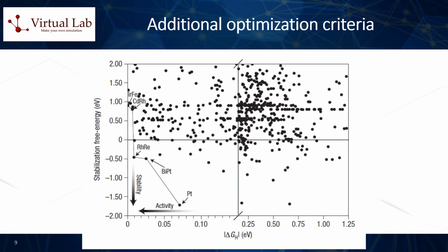In order to narrow down the search space of all possible material candidates, it is convenient at this stage to introduce additional optimization criteria for identifying highly performant catalysts, such as the material's resistance to effects such as corrosion and oxidation in an electrochemical solution environment. In the particular example study considered here, the Gibbs free energies corresponding to the most common of such degradation phenomena were therefore also calculated with DFT methods, and combined with the previously obtained results on the free energy of hydrogen adsorption.